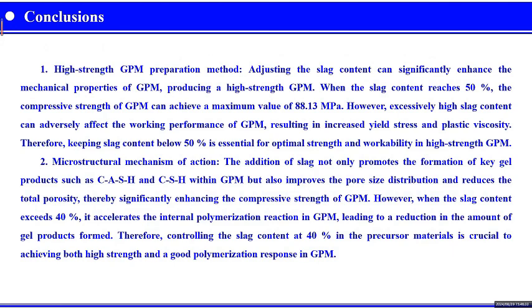The second, microstructure mechanism of action. The addition of slag not only promotes the formation of key gel products such as C-S-H and C-A-S-H within geopolymer mortar, but also improves the pore size distribution and reduces the total porosity, thereby significantly enhancing the compressive strength of geopolymer mortar.